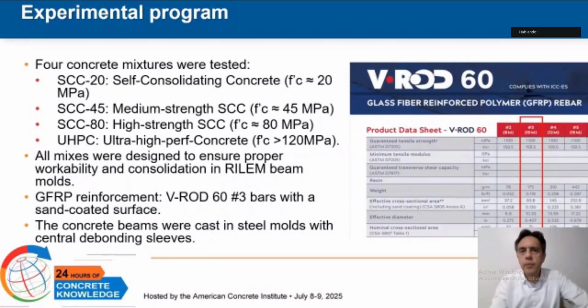The experimental program included 4 concrete mixtures that covered a wide range of strengths, from conventional self-consolidating concrete, SCC, with a compressive strength of 20 megapascals to ultra-high performance concrete with a compressive strength exceeding 120 megapascals. The goal was to isolate the effect of concrete strength on the bond with GFRP bars while keeping all other parameters constant.